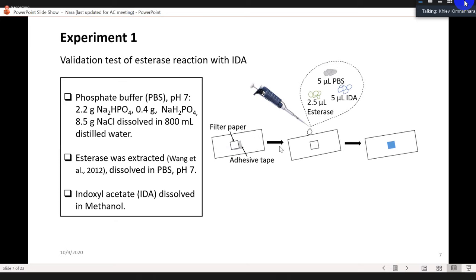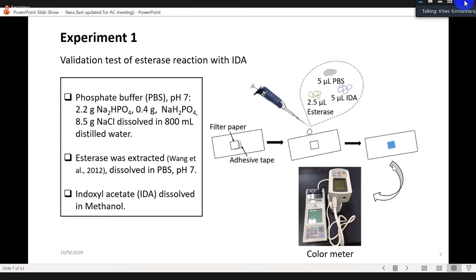After that, I apply the enzymatic reaction by mixing 5 microliters of phosphate buffer and 2.5 microliters of esterase. Then it was mixed with 5 microliters of indoxyl acetate. The final solution was spotted on the test zone of the paper-based sensor. After the enzymatic reaction happened, the color changes from colorless to greenish blue, and then from greenish blue to blue like this. After that, a colorimeter was used to evaluate the color changes. The colorimeter is very important for quantitative analysis besides our eye observation.